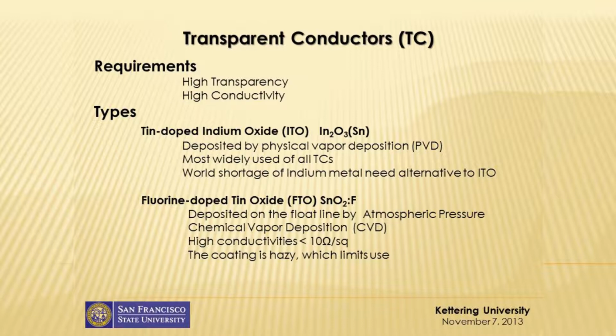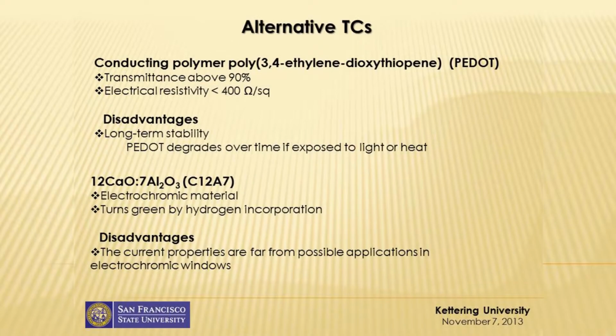The disadvantage of the FTO coating is the haze. It is a little bit hazy. It's not as transparent as ITO. This makes it limited in use, especially if you are using it for window applications. There are also alternative transparent conductors. They are organic transparent conductors. Conducting polymers, we call PEDOT, have transmittance above 90%, which is good, but electric resistivity is higher compared to the inorganic material. It's less than 400 ohm per square.